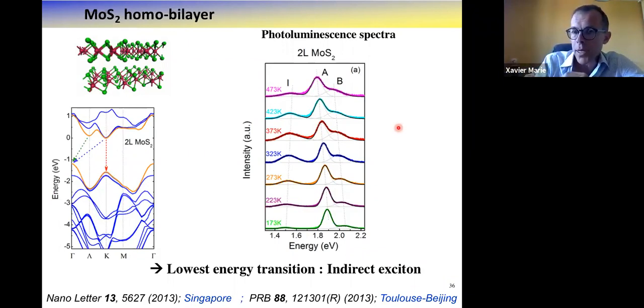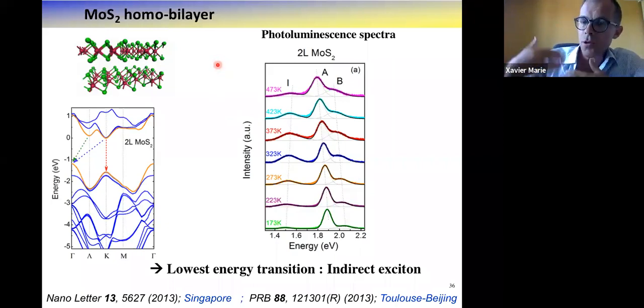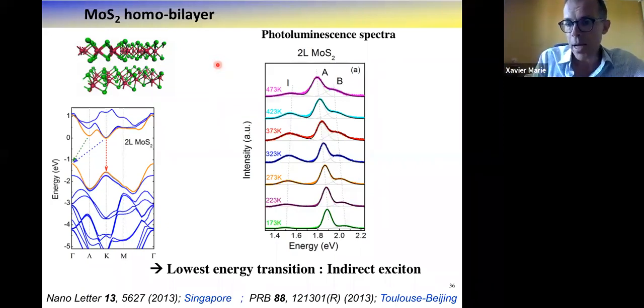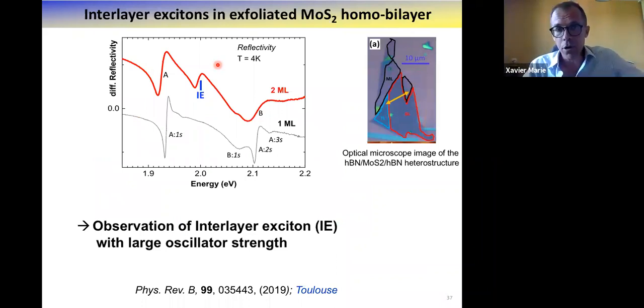But one of the open questions is, can we evidence some coupling between the two layers in the K valley, analyzing this transition occurring in the K valley? So again, in the first generation of samples, we failed to observe this, but thanks to hBN encapsulation and much narrower line widths, I will show you some results, again obtained in collaboration for most of the work with Jena and also the University of Basel, that we can evidence this interlayer exciton.